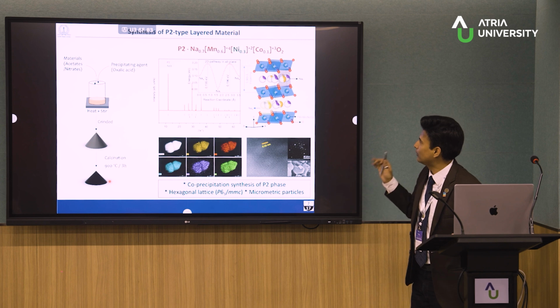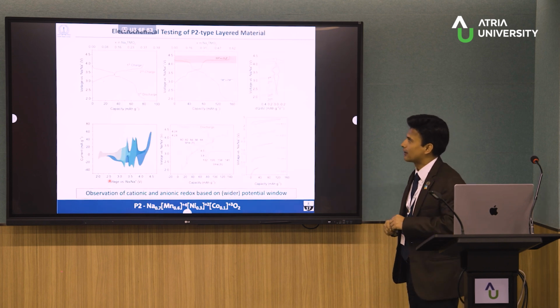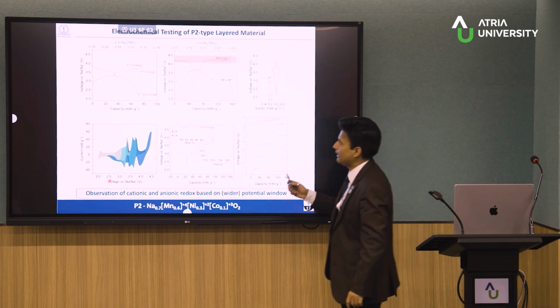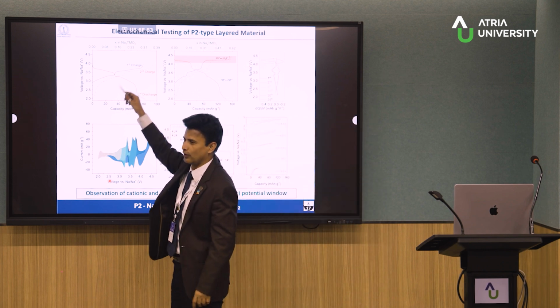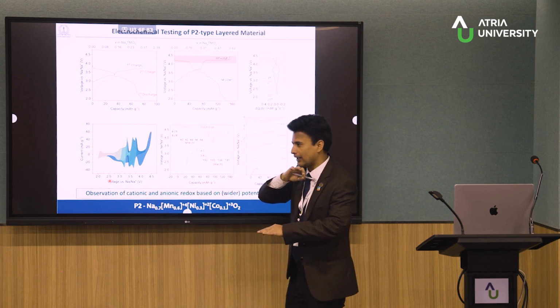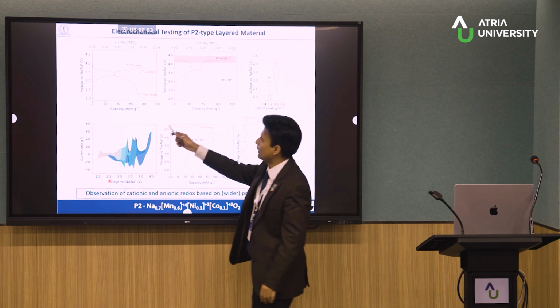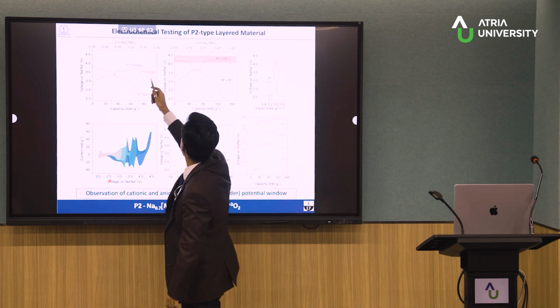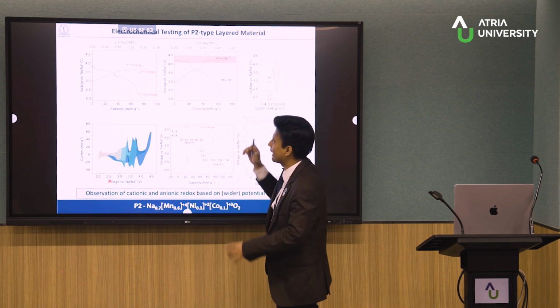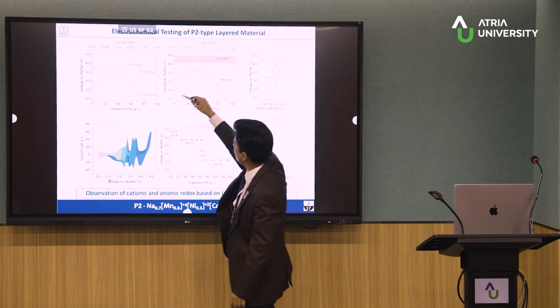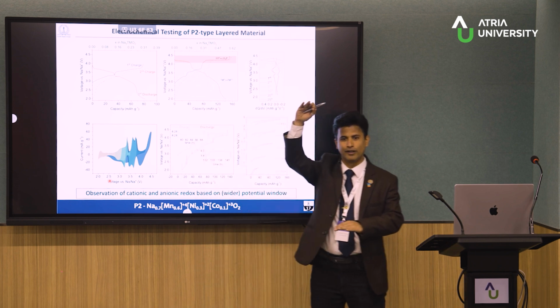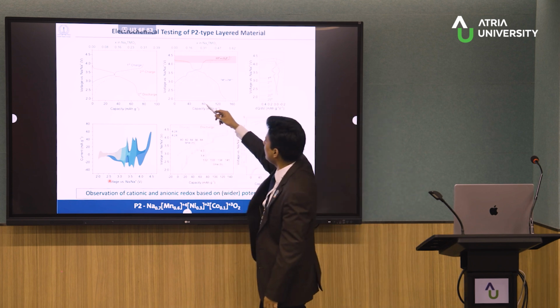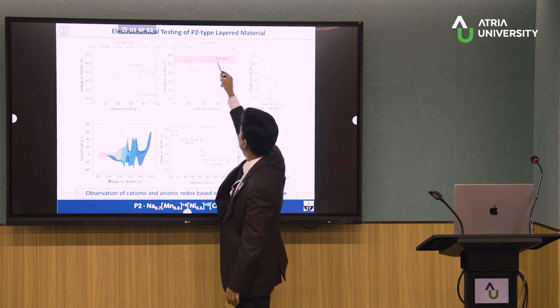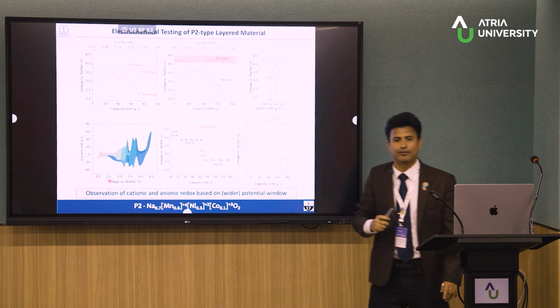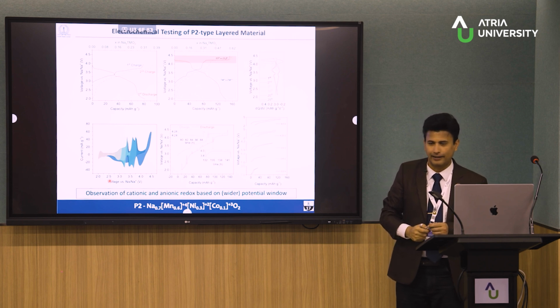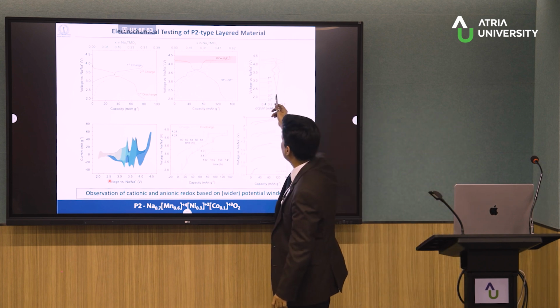Now, this material, without any optimization, when we did some half cell study, initially we limit the voltage up to 4 volt only. When the voltage is low, only the cationic activity works. So there we can get some nice activity here, which is basically because of the transition metal cationic redox. Now, if we go to little high voltage, if we hit up to 4.5 volt, then what happens is, in addition to the cationic activity, also we get some extra peak, which is because of the oxygen or anionic redox activity.